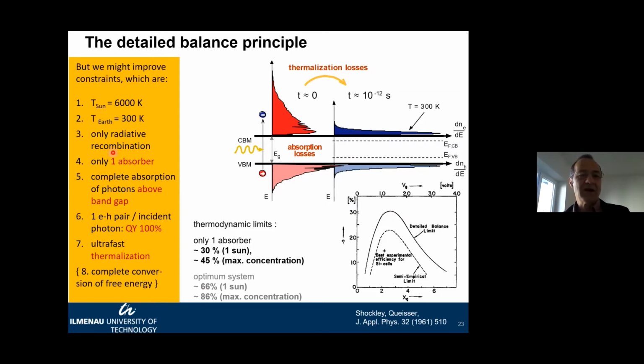I listed here the boundary conditions which lead to the detailed balance principle. This is that the sun, of course, has a certain temperature, that our planet has a certain temperature, that we are only regarding radiative recombination, that we have only one absorber, and that we completely absorb light. Each photon produces one charge carrier, or let's say one electron-hole pair, we call it. And also that we have ultra fast thermalization. But we can change this. We can change, in particular, the point that we have only one absorber. And this I would like to show very briefly.